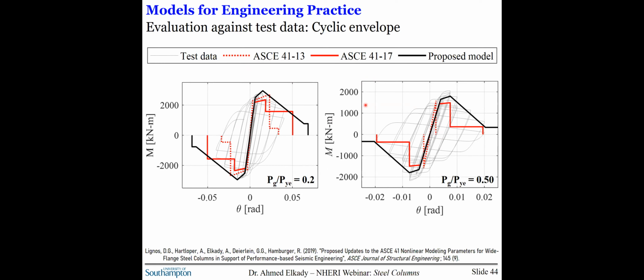These are a couple of illustrative test data comparisons with respect to the first cycle envelope that we proposed. Also in the same plots, we superimposed the envelope curve based on the previous and current ASCE 41 standards. And these are for two specimens with different axial load levels under symmetric loading. As you can observe here, ASCE 41-13, the previous version, used to overestimate the elastic stiffness.